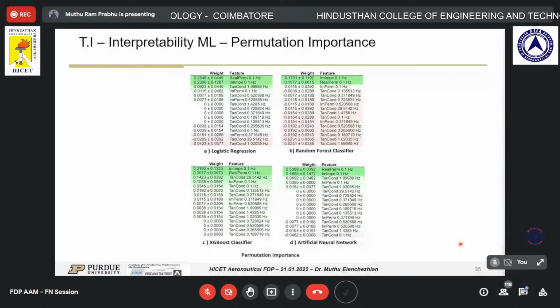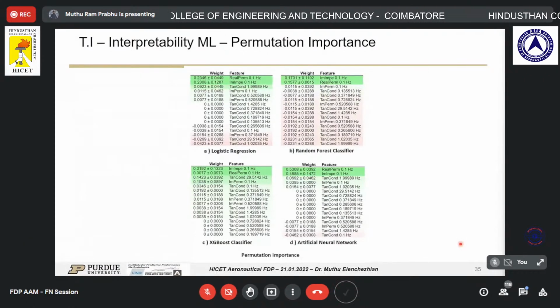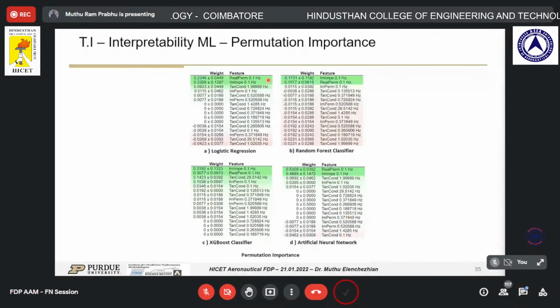As I mentioned during my previous slides, I also wanted to see the interpretability of these models being developed. That is, I wanted to know which feature actually contributed to predicting the output of my model. To analyze that, we can do permutation importance. What permutation importance does is it artificially changes the values of the feature, and based on that, it predicts the output of the model. Based on how much the error percentage changes, the weight for each individual feature is obtained. In all the 4 models developed, we can see the lower permittivity, that is the 0.1 hertz real permittivity, or the imaginary permittivity values, were the most contributing features for my model completely.